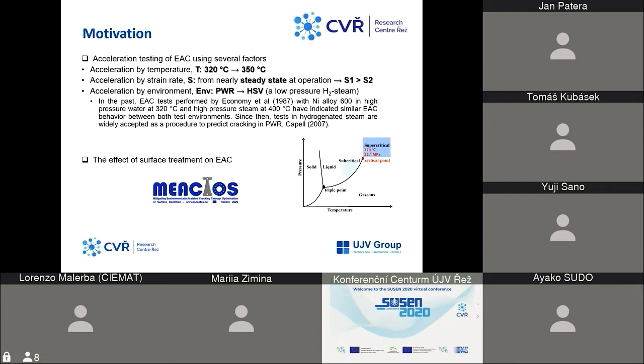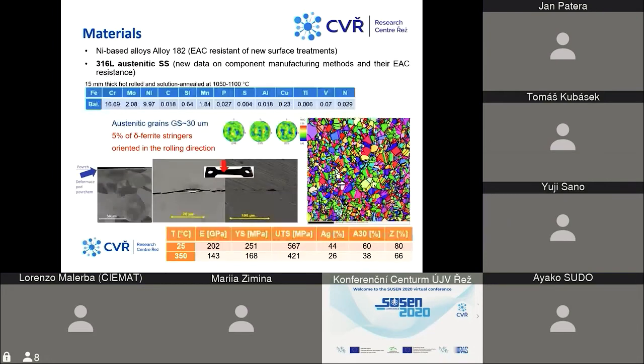Also, the effect of surface treatment on the environmental assisted corrosion is the main goal of the MEACTOS project I've already talked about. So for this investigation in the MEACTOS project, we use two types of materials. The first one is a nickel-based alloy 182. This material was chosen to study the EAC resistance of new surface treatments applied for this alloy, and also the conventional 316L austenitic stainless steel. It was used more to gain new data on the components manufacturing methods and their resistance to the environmental assisted corrosion.